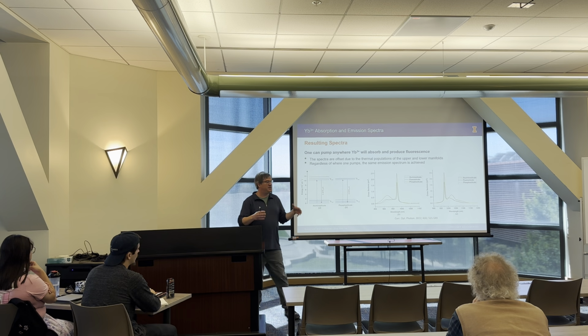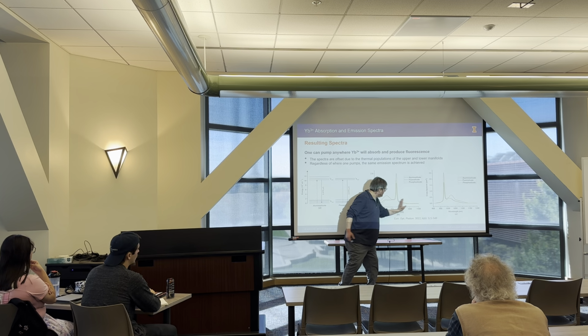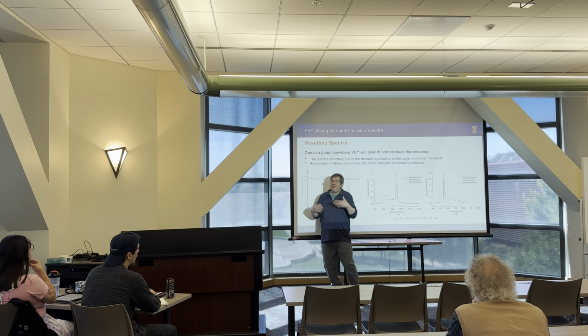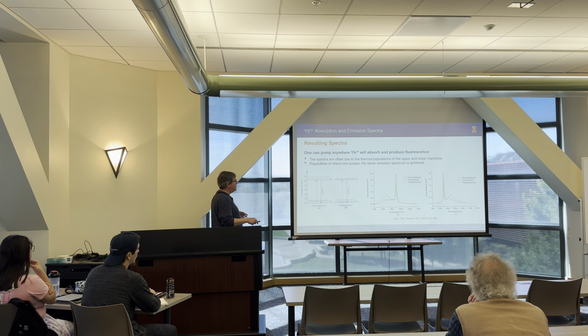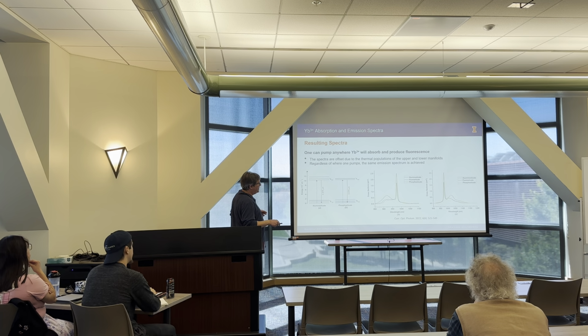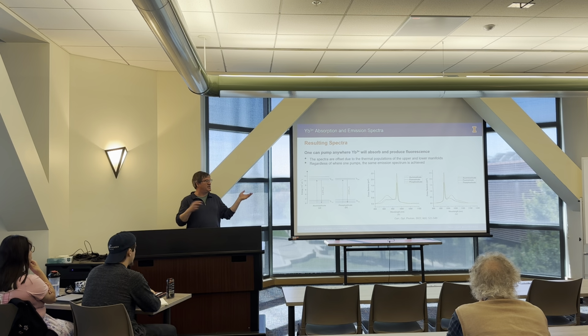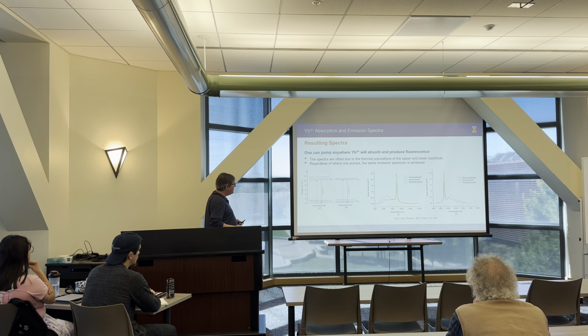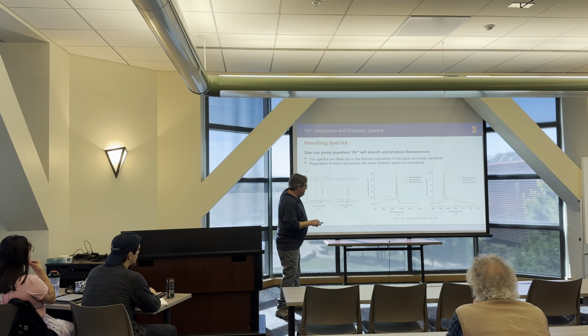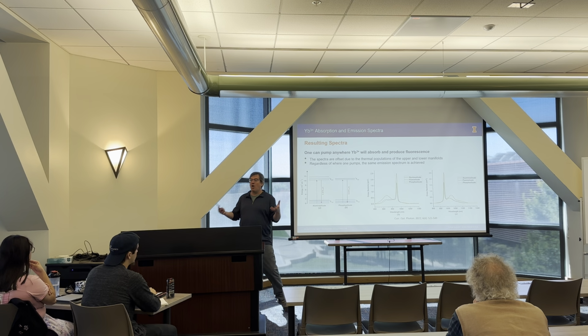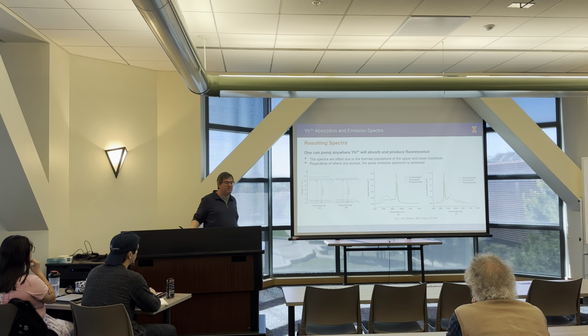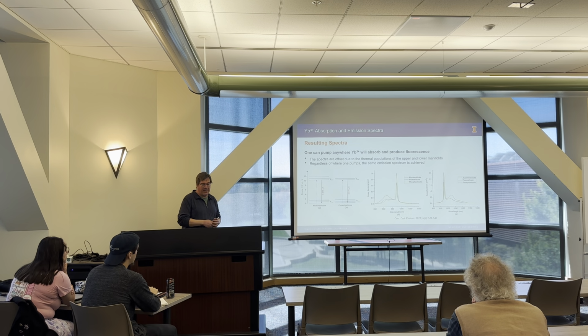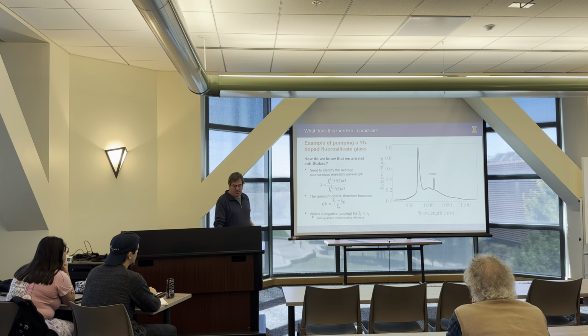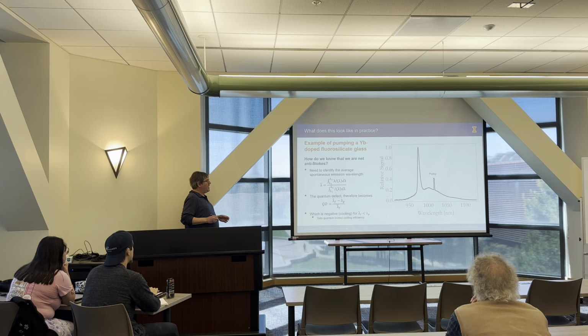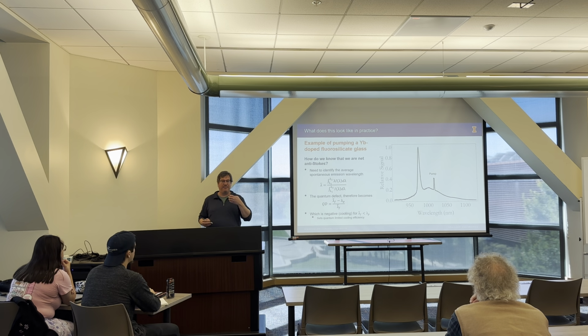You're always going to produce photons at an energy that's less than where you started. Whereas as you start marching this way, and again, this fluorescence spectrum is independent of where you pump, if you choose a pumping wavelength out here someplace, then you can produce this entire spectrum, which is almost entirely anti-Stokes, and you're extracting energy. The trade-off, of course, is that as one marches towards longer wavelengths, even above 1050, the absorption is so low that you need large volumes of material to absorb sufficient power to see any appreciable cooling. So those are the emission and absorption cross sections, and hopefully that gave all of you a little bit of respect for what that looks like.